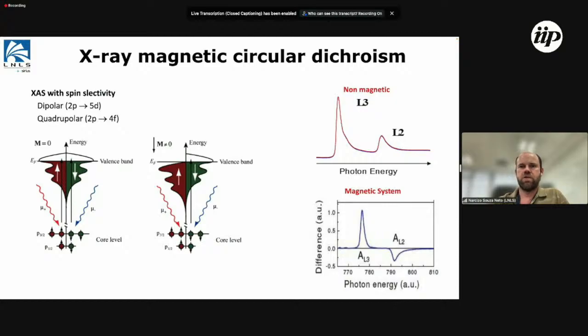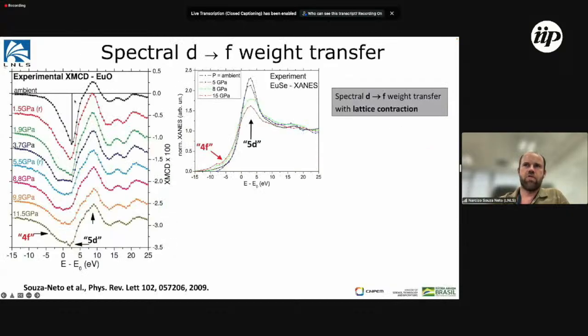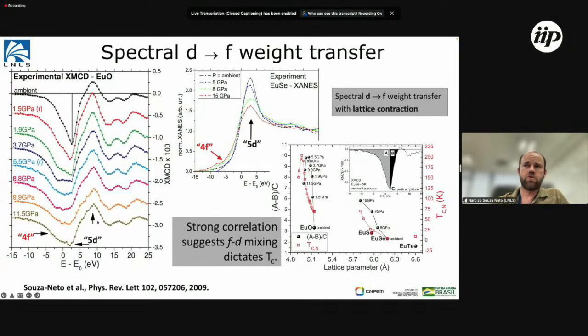But not only that, we can even look at, for example, the dipole selection, and in this case it was XMCD with pressure. When we changed the pressure, the shape of it was changing, and that actually was due to an electronic change between the 5Ds and the 4Fs, and we saw similar things. And this electronic change, after we quantified it, was related to an increasing ordering temperature of the material.